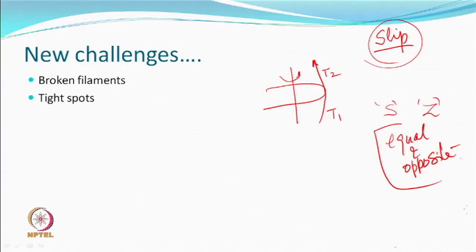Whenever you want to twist a material, there is an opposite force or opposite torque getting generated within the material, which is resisting. So, you have a fixed force of friction which is giving a certain torque, and now you have opposing things also, and therefore it is a catching up game. The surface speed of the yarn cannot be more than the speed of the disc. It is only following. When you start the machine from zero, it starts picking up, goes up to a point, and then this will happen for whatever reason: fluctuations in voltage, fluctuations in vibrations, and resistance also. So, this new problem is there.